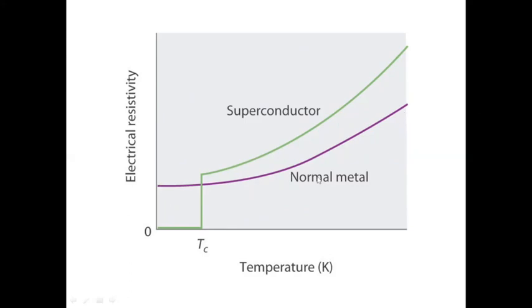Here there are two very unique features. One is that at low enough temperature, or at zero temperature, the resistivity tends to zero, not zero, it tends to a constant. Similarly, at higher temperatures, you can see it shows a tendency of saturation. At low temperature, that saturation tendency is associated with the quantized lattice vibrations getting frozen out as you go down in temperature. That's why this saturation tendency shows up here. However, if you go to higher temperature, there is a criterion called the Mott-Ioffe-Regel criterion.